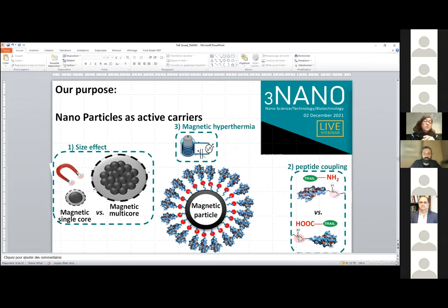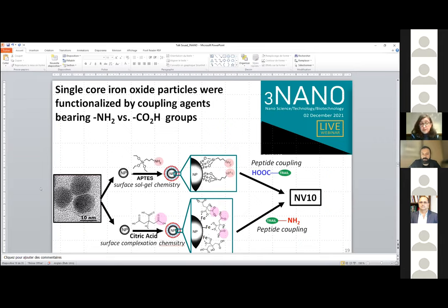We attached TRAIL to the particles always using peptide coupling, but in one case we use an amino group from the TRAIL and in another case we use a carboxylic group. For that, we decided to focus on the smallest particles, the 10 nanometer sized ones. And for a part of our powders, we used APTES, aminopropyltriethoxysilane, and then surface sol-gel chemistry to attach amino groups on their surface. And for the other part, we used citric acid. You can see here its formula. And we used surface complexation chemistry in order to attach carboxylic groups at the surface of the particles. And these two modified particles were then coupled through EDC-NHS peptide activation to TRAIL, in one case using a carboxylic group, and in another case an amino group.